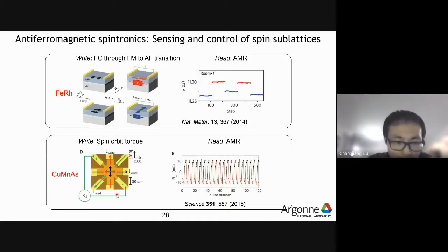So shown below is another application of antiferromagnet, and this is a copper manganese arsenic system, and this is also a metallic antiferromagnet. People in this case use a spin-orbit torque to manipulate the Néel axis. And in the end, people also use the AMR effect to read out the direction of the Néel axis.